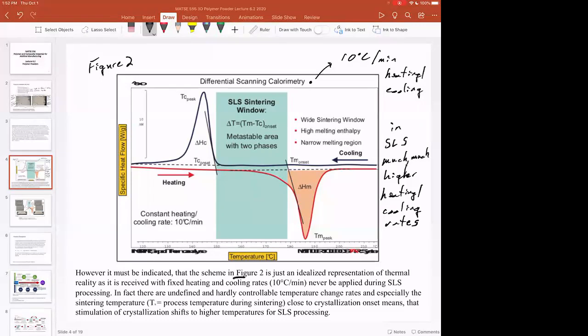So it says the scheme in figure 2 is an idealized representation of the thermal properties of this polymer. And so this is the issue where the measurement that you're making analytically in DSC is somewhat representative of what you could expect from the material, but when you're processing it, things are happening much faster. And we know that processing speed can have an influence on polymer properties. And so they talk about this DSC is at 10 degrees C per minute, but this never occurs during SLS. And so the sintering temperature or the processing temperature during sintering is going to be very close to the crystallization. And so that means that the crystallization is going to shift to higher temperatures for SLS processing and be more in this region.